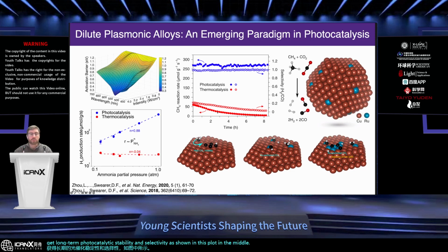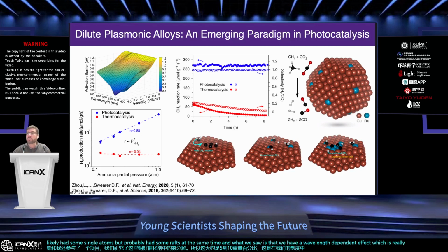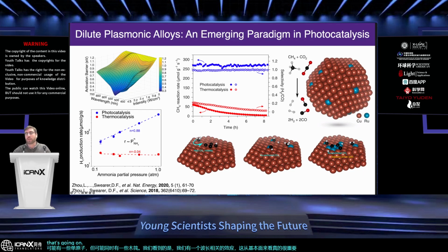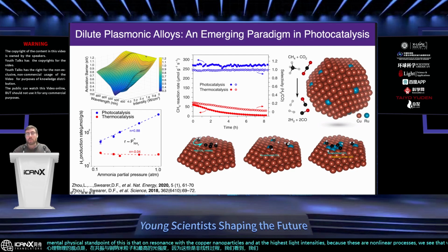Lee and I also worked on a project where we looked at ammonia decomposition in these copper ruthenium catalysts. So this was about 5 to 10 weight percent, which was in a regime where we likely had some single atoms, but probably had some rafts at the same time. And what we saw is that we have a wavelength dependent effect, which is really important from the fundamental physical standpoint of this, is that on resonance with the copper nanoparticles and at the highest light intensities, because these are nonlinear processes, we see that we can have a reduction in the activation barrier, from about 1.2 eV all the way down to 0.3 eV.